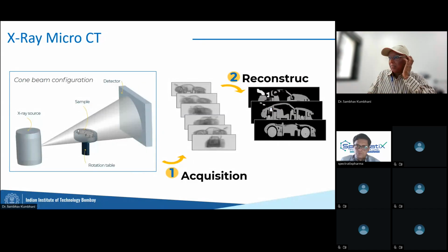The rear part of the car is a very different material than the rest of the car, because it is much whiter. The whiter it is, the harder and stronger the material is, and the grayer it is, the softer the material is. So you can identify all that using the shades only. So first start with CT, then do an XRF. Again, it's a surface technique, but it can confirm a lot of at least initial elemental information. Then you do XRD. Then you'll be able to know what the material is.